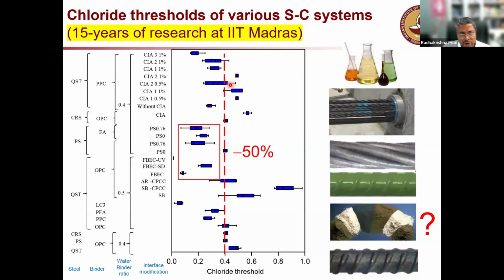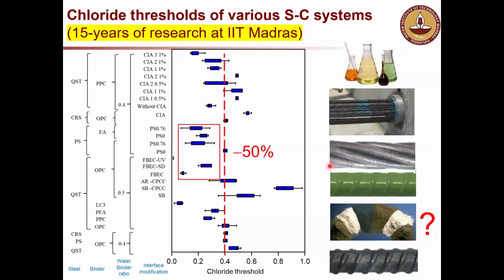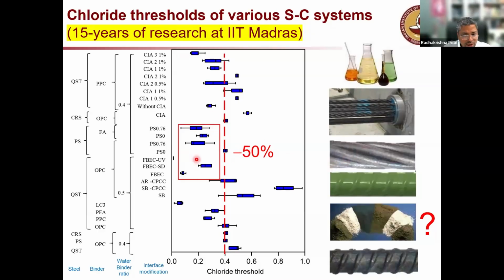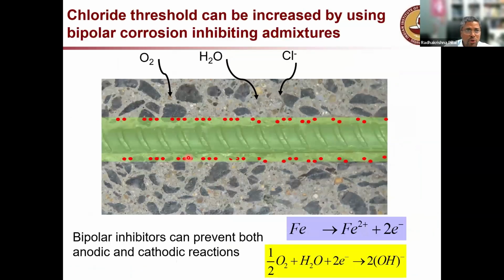One important point is for pre-stressed concrete, the chloride threshold is significantly less than the other systems. And also for rebars which are coated with fusion bonded epoxy material, there is this green color bar which you might have seen in many construction sites. There also you have significant reduction in the chloride threshold. What it means is such systems could start corrosion at a lower chloride level, which is something one has to look at. Now, if you talk about increasing or enhancing the service life, we have to increase the chloride threshold.